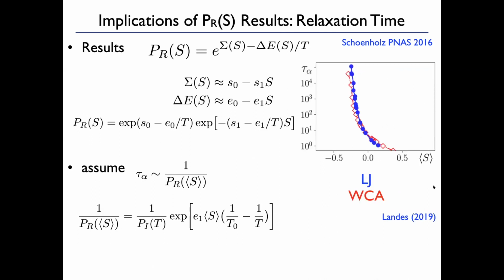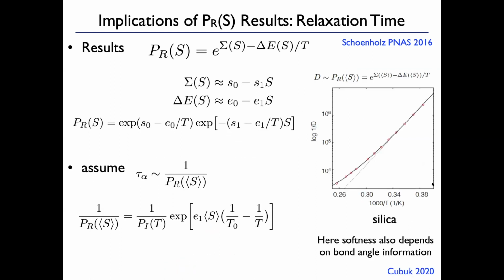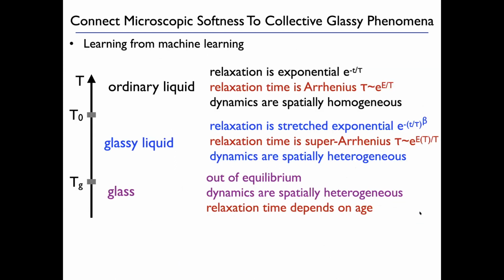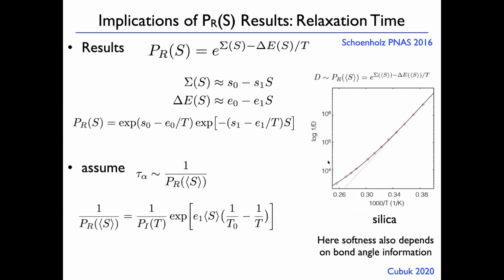And this works for Lennard-Jones, it works for the Weeks-Chandler-Andersen potential. It works for silica. I can do the same thing for silica. This is the diffusion coefficient, which I say is like the inverse relaxation time. So it's the probability of rearranging at the average softness. The points are the measured values for the diffusion constant from the simulation, and the curve is what we get from our prediction. It really works.